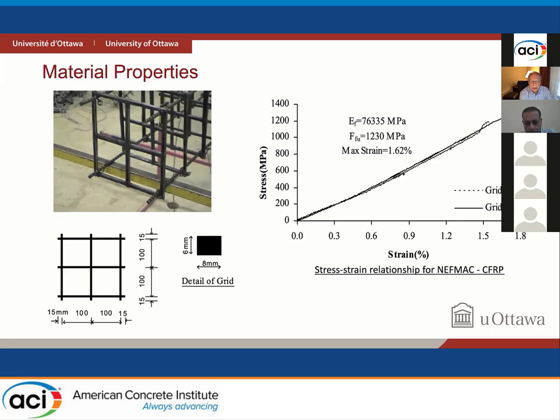However, one has to understand that the critical point in these grids were the corners. And in this research, we did not observe any transverse reinforcement failure. However, in another companion research where we tested grids with steel reinforcements, longitudinal steel reinforcement, the corners started failing at about 700 MPa. So this 1200 MPa should not mislead you. That's the material capacity, but not necessarily lateral load capacity when it comes to restraining longitudinal reinforcement against buckling or